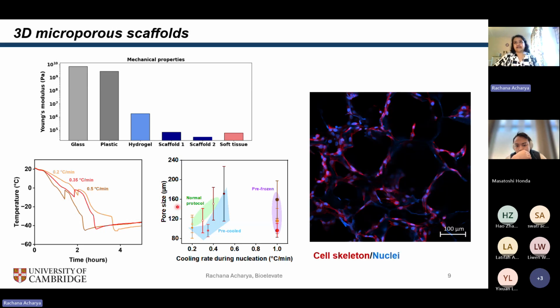And this is quite important because, as you can see, this is a confocal microscopy image of the scaffold with the cells growing in it. You can see that when the cells start attaching, they line the pores of the scaffold. So it's quite important that we have a pore size which is compatible with the kind of cells we are growing, so that the cells don't fall through, or are not just stuck at the top and don't penetrate into the depth of the scaffold. So that's the idea.